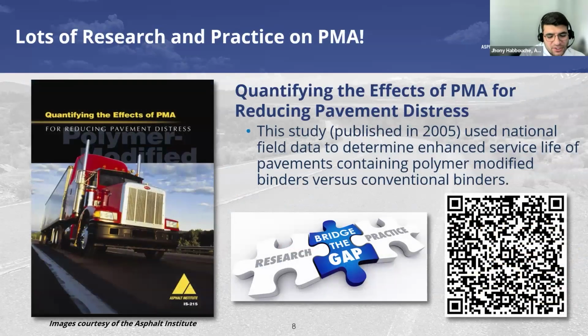A lot of research and practice has been done for over 50 years on the use of polymer modified asphalt. One of them I would like to mention is the work that was completed by the Asphalt Institute back in 2005 by their affiliate committee on quantifying the effects of polymer modified asphalt for reducing pavement distress. It was based on sections that had PMA, whether in their top, intermediate, or base layers, and they were able to prove an extension of at least 10 to 15% in performance life when these are used properly.